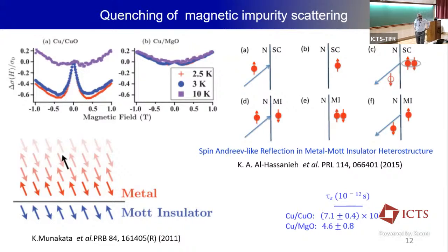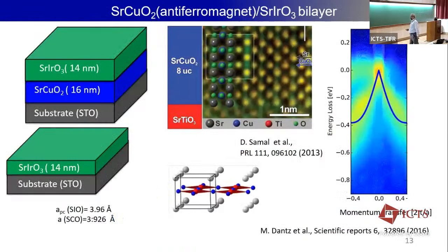So this motivated us to look into SrIrO3, because in copper they see a very different response when they put copper on top of an antiferromagnetic insulator. As I mentioned, there was no clear-cut transport evidence showing that it is a Dirac-like system. So we put SrIrO3 on SrCuO2. SrCuO2 is an antiferromagnetic insulator, and we also grew a test sample without any antiferromagnet in between.